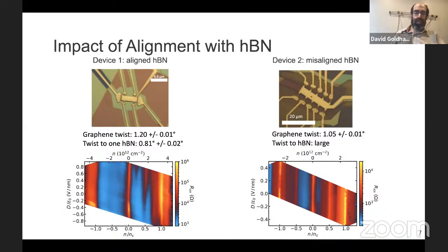And at first glance, it looks quite similar. Again, we have basically vertical features, but you can see that actually those features do change with the electric field normal to the plane and in an asymmetric way, which suggests that the structure is asymmetric. Indeed, that's because of alignment with one of the boron nitrides. It's not the same on top and bottom.